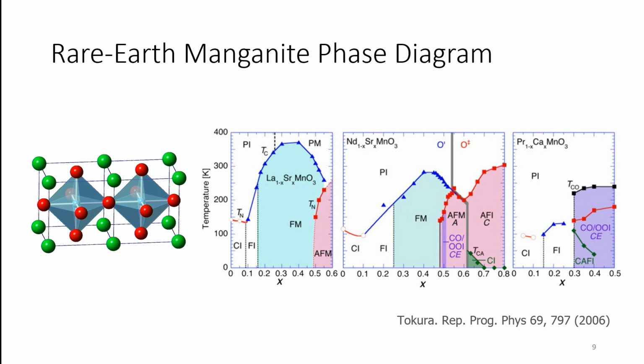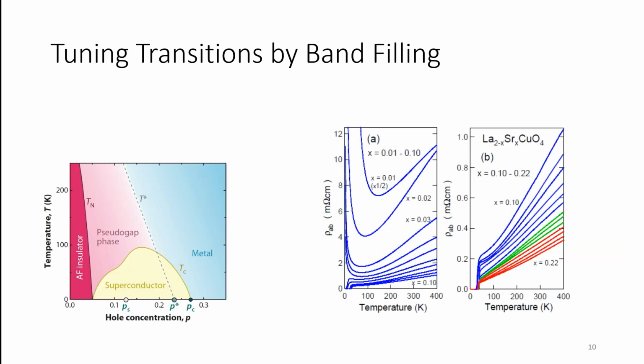So the point here, if you take anything away from it, is that in these systems you have a lot of degrees of freedom. You can change the charges you put at these sites, the net charges here. You can also change the structure, and that can lead to very different phases, both magnetic and electronic, of these systems. So when you change how much lanthanum and strontium you have at those corners, because manganese can also have multiple charge states, you're effectively changing the ratio of manganese in different valence states.